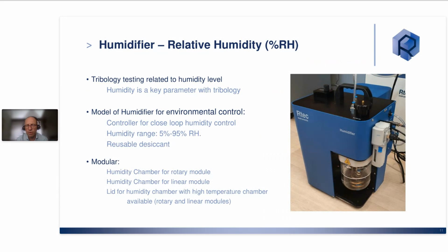And it's true that people may forget that in tribology, the coefficient of friction may vary very strongly with the level of humidity, meaning that if you test in a different country, you may have different results if you forget to record the level of humidity in the laboratory. But with this kind of option, we can control the level of humidity and in fact reproduce different levels of humidity in order to see the variation of the coefficient of friction as a function of humidity.